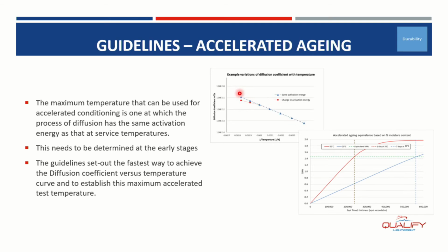So if that's a linear graph, we can see that the diffusion at each of those temperatures is using effectively the same process, and has the same activation energy. If the curve deviates from that, we can then understand that a different diffusion mechanism has opened up. That might be due to the rearrangement of free volume, etc., over time.